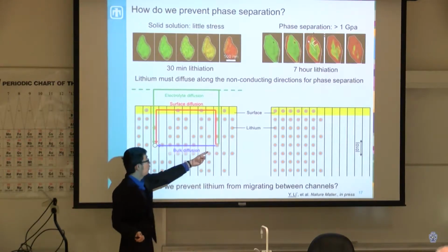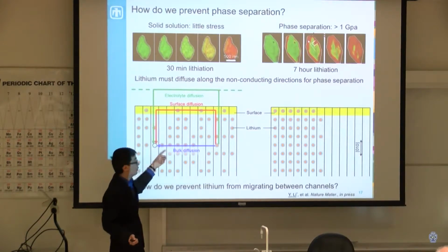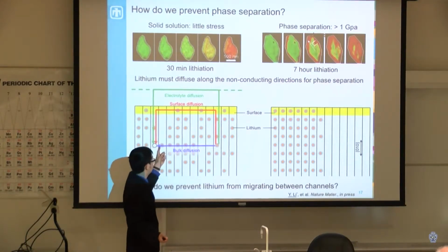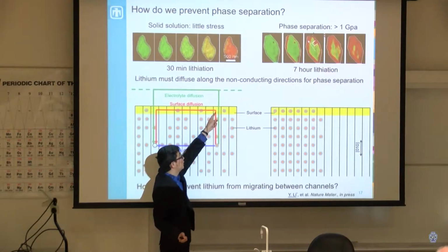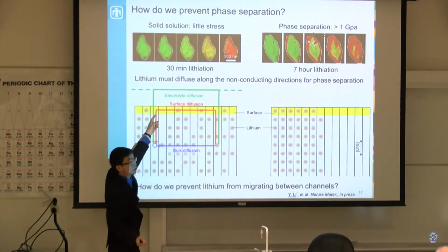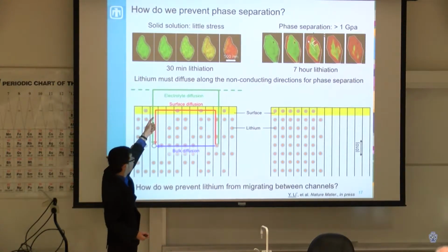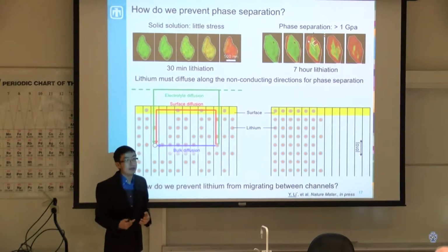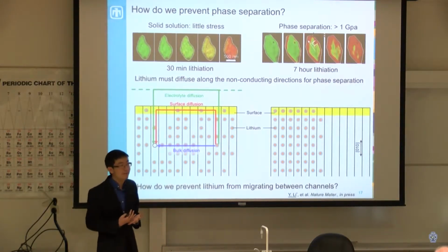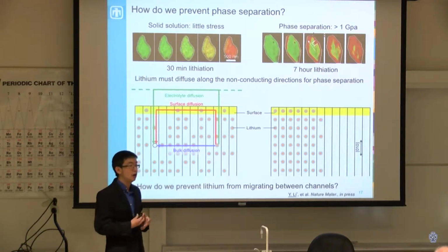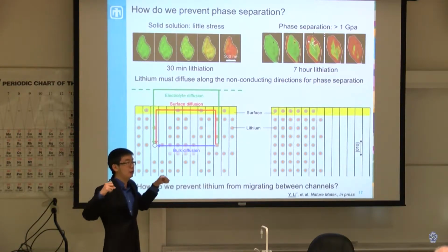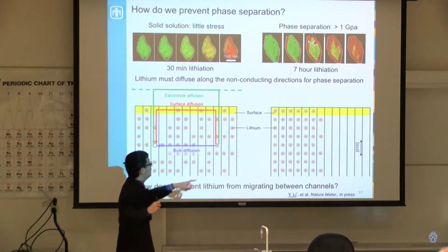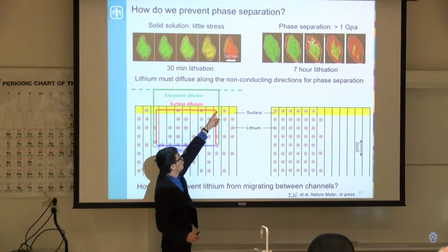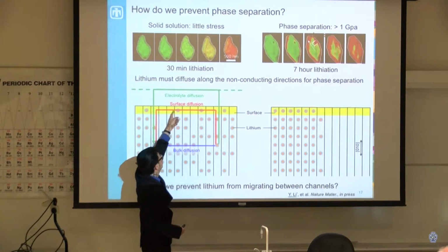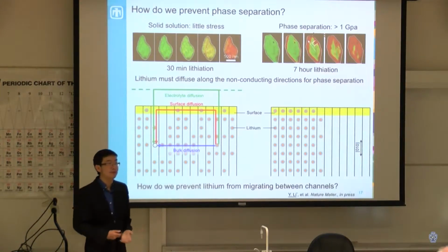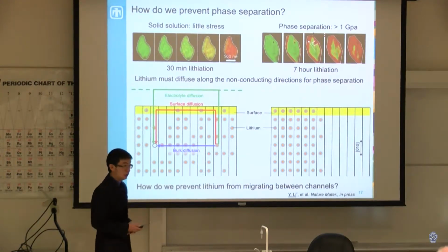So for lithium to go from one part of the particle to another part, what actually happens is that it can't really just go this way, but instead it goes up to the surface and can move across the surface, which forms an extended defect within the material, and goes into the bulk. The mechanism we think is happening is that our electrolyte molecules are basically helicoptering the particles from one side to another. When we have electrolyte molecules, the particle can move very quickly along the surfaces, and when we don't have this liquid electrolyte, it actually moves very slowly.